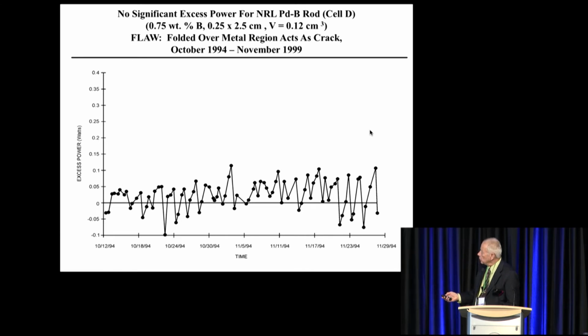This is another experiment that did not produce excess heat. We could see a flaw in it before we started, so we wondered about it. In the swaging, a large part of the palladium was folded over and made a crack. It almost went the entire length of the palladium-boron rod. And sort of like we expected, we did not see excess heat in this one.